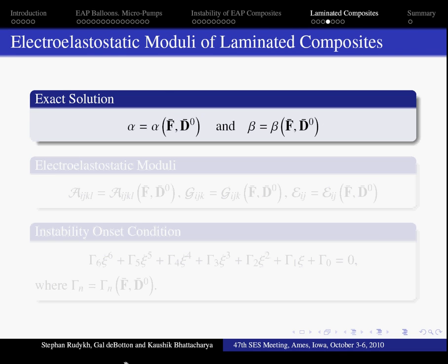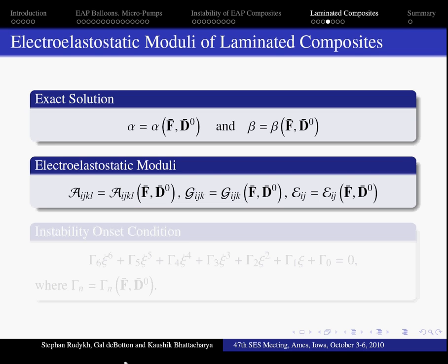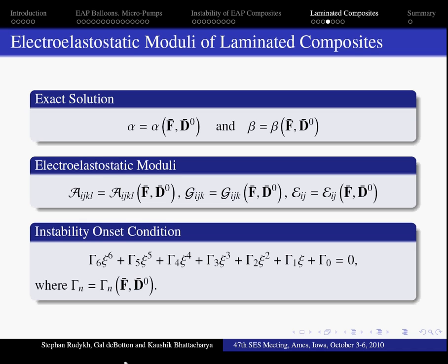And they are function of mean nominal electric displacement and deformation gradient. And since we have the exact solution, we can obtain the electro-elastostatic moduli. And they provide us the coefficient of the polynomial equation. And the onset of instability can be estimated.